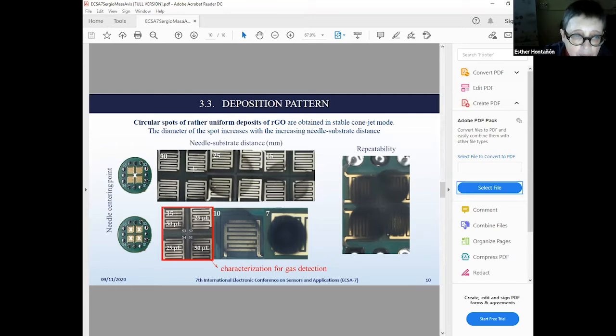So we started performing experiments at relatively long distances in order to cover the surface of the 4 sensors simultaneously in only one step. And in these experiments, the needle was centered and pointing to the center of the substrate. You can see here that the size of this spot basically covers the diameter of the substrate. When you reduce the distance, then you get smaller spots. At some point, the spots are so small that they approach the size of the individual sensor.